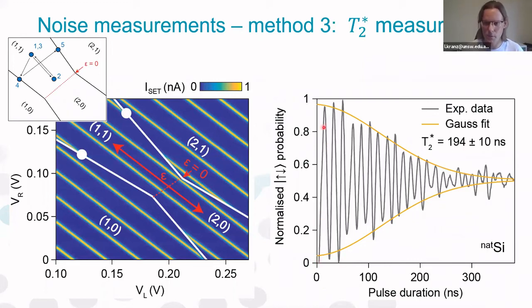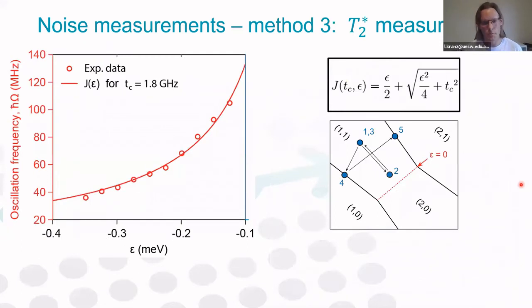And the frequency of these oscillations directly corresponds to the exchange interaction J. And we see a decay in oscillations, and by fitting a Gaussian function, we can calculate the dephasing time T2 star. Okay, so now we repeat this experiment at different detuning positions, and this allows us to plot oscillation frequency as a function of detuning. And as expected, if we increase this detuning, the overlap between two electron wave functions is larger, and this leads to faster oscillations.